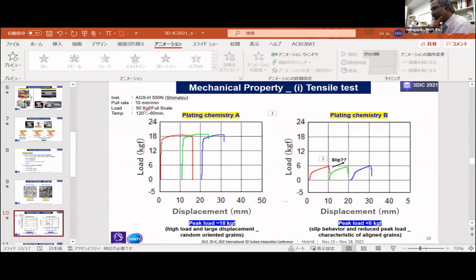On the other hand, for the new one, we observed nearly one-third, just 6 kilogram force. It's quite malleable and ductile. The Young's modulus may be very low. In addition, if you carefully look at this, before going to the break point, your conventional one is just a curvature. On the other hand, using our new chemistry, the plated grains always show some slip-like behavior. It normally occurs in some two-dimensional material or some oriented material. So your planes are slippy. So basically it confirms our grains are aligned in some direction.